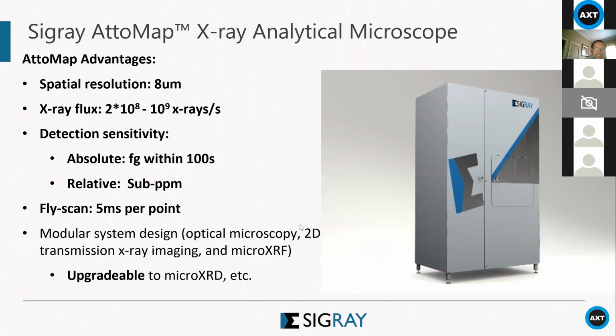So these are some specifications of the system. Spatial resolution down to 8 micron, and flux over 10 to the 8th, comparable to some second generation synchrotron beamlines. We have very high detection sensitivity down to femtogram, and relative sensitivity can go to sub-ppm. We do fly scan at 5 milliseconds per point. It's a very modular design with, as I said, an optical microscope and transmission X-ray camera, and we can also upgrade later on to do MicroXRF and MicroXRD.